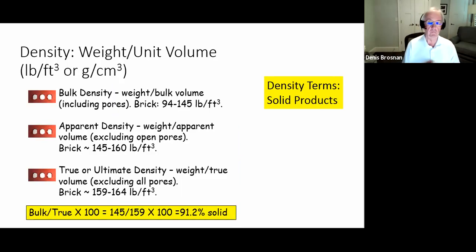Well, density. Density is weight per unit volume. There are several terms that we use, so we can express it in inch-pound units or metric units, however you like to do that. But the first of these terms is bulk density. That's the weight over the bulk volume, the physical dimensions of the ceramic part. The bulk volume includes open pores and closed pores, pores that have been closed in the firing process. So the bulk density is that of the bulk, meaning the weight divided by the bulk volume of the ceramic. It's usually the lowest density.